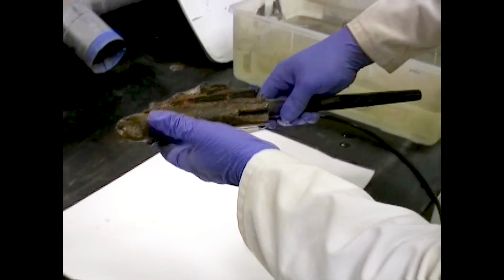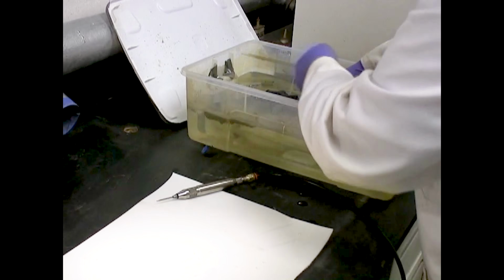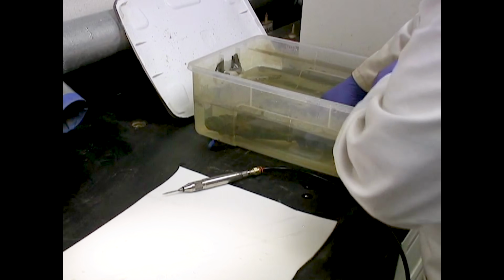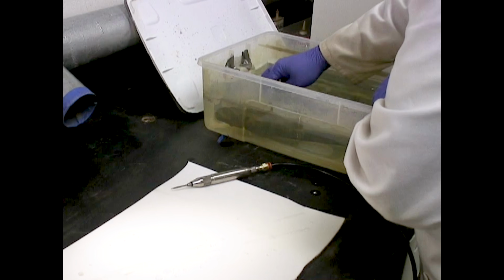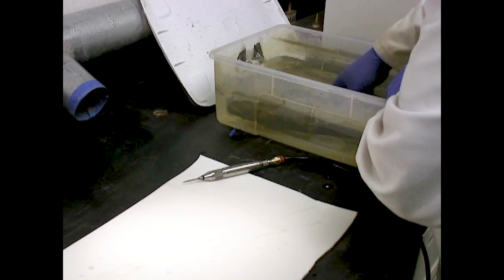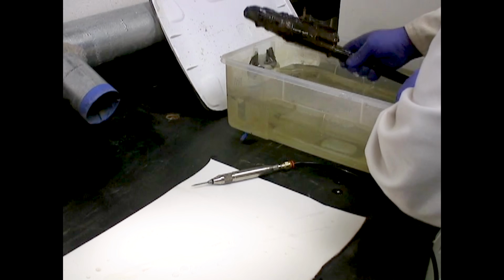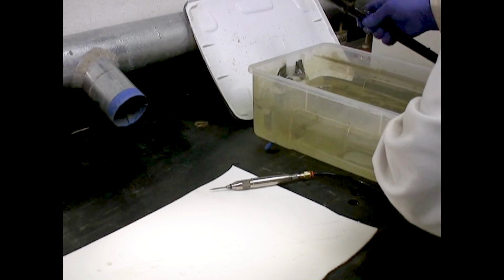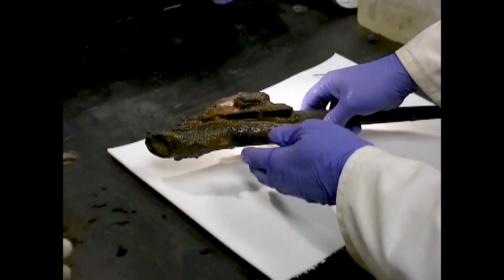Because the pistol came out of a well and was waterlogged, perhaps the most challenging aspect of the conservation treatment was keeping the pistol wet while getting the work done. Every 2 minutes we had to dip the pistol back into deionized water to ensure that the wood wouldn't dry out, but also to mitigate potential corrosion of the metal as more oxygen was reaching the metal surface.